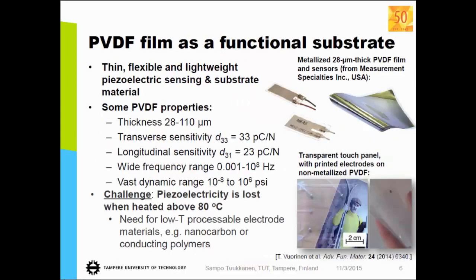And this PVDF in the piezoelectric form is commercially available. From the US, you have a company called Measurement Specialties where you can buy the ready-made sensors or the films, flexible, large metallized films. But what was interesting for us was to buy this non-metallized film, so then we can take the film and print the electrodes on top.